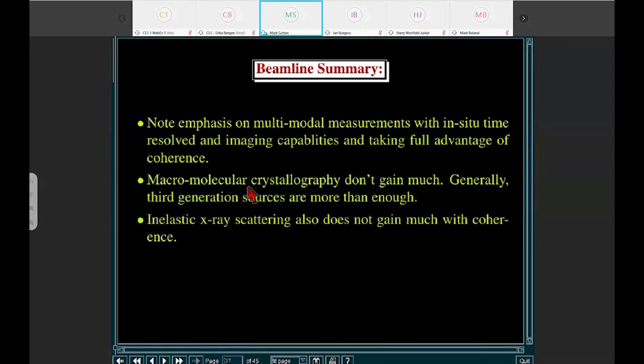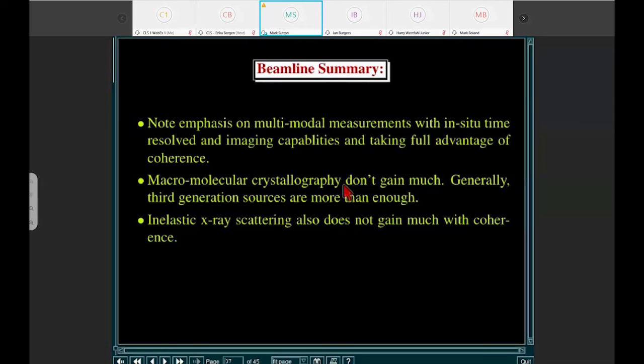I'd just like to point out, macromolecular crystallography is more dependent on flux than it is on coherence. And not many of the new beamlines take advantage of the coherence that comes from these sources. They only take advantage of the increase in flux, if there is any. Inelastic X-ray scattering also typically doesn't take into account coherence. It's an incoherent type of measurement. And the main reason you win in these two is you can focus the beam down to a smaller spot because coherence allows you that, and that's really the only gain that you get in these kinds of beamlines.